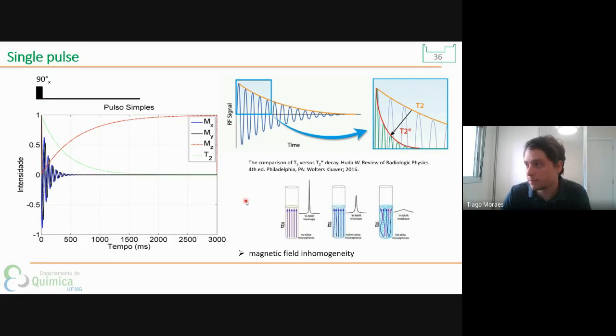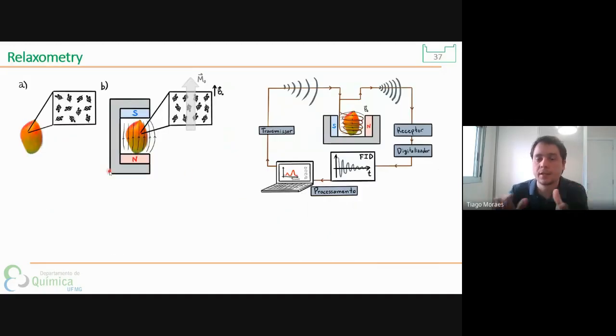I will show in some other slide, because in some low field NMR equipment, the bore of the equipment is bigger. So for example, when you want to insert a whole fruit inside the magnet, the bore is bigger, so the inhomogeneity in your sample will be higher, right? So we need to remove this effect of the inhomogeneity field. And here is just a picture showing again that we apply some pulses in our sample, here, for example, a mango fruit, and the nuclear spins of the sample respond, and we detect the signal, and we do the analysis with the relaxometry methods that I will show.